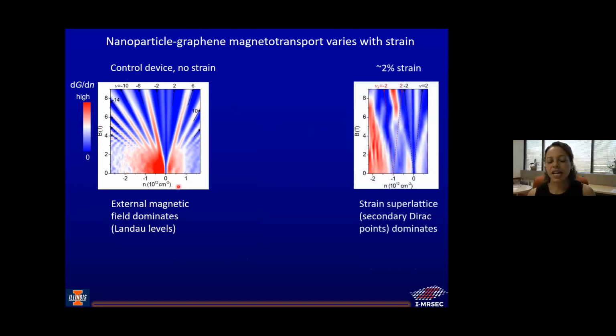Now we take a device that has a lot of strain. How do we know the strain? We do Raman spectroscopy. We can't really control this. We're keeping the nanoparticle size the same. We're measuring Raman to see what the average strain is. Here we have about 2%. And what we see are these strong secondary Dirac points, dispersing in magnetic field just as you'd expect for a superlattice. Okay, so this is really nice. This shows us that we have a superlattice with secondary Dirac points that disperse with magnetic field as expected.